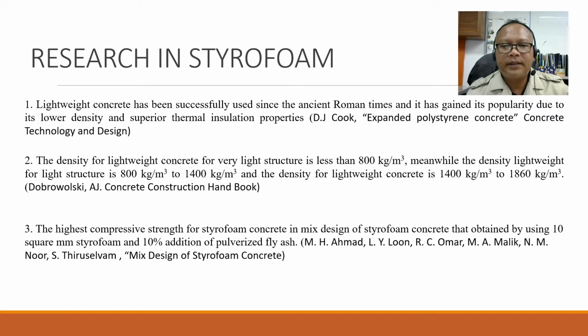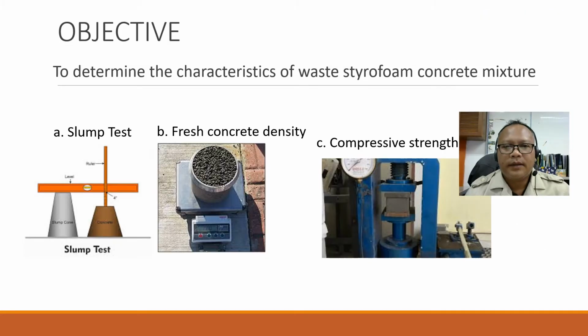MH Ahmad stated in his research that the highest compressive strength for styrofoam concrete was obtained by using 10 mm styrofoam and 10% addition of pulverized fly ash. The objective of this research is to determine the characteristics of the styrofoam concrete mixture. Firstly is the slump test, secondly is fresh concrete density, and third is compressive strength.